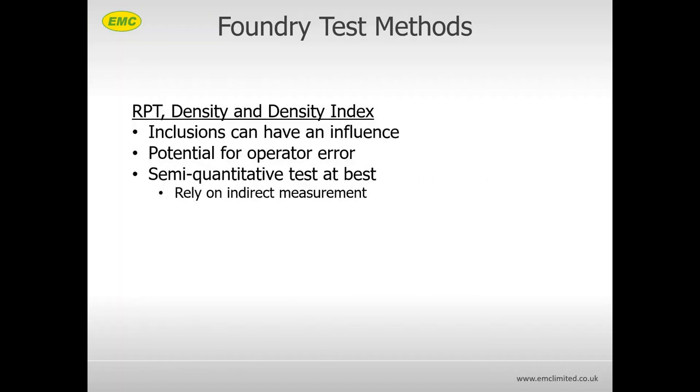These tests have served the industry well for many years, but there are drawbacks. Inclusions can have an influence as they provide nucleation sites for the hydrogen. And there is the potential for the operator to influence the result. I did watch once an operator happily writing down the required density index rather than what it was actually measuring.